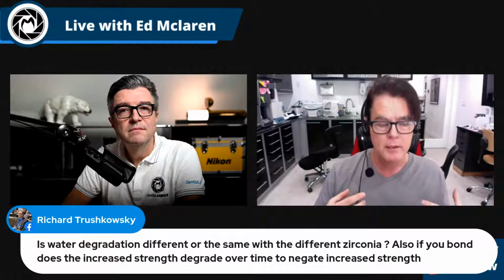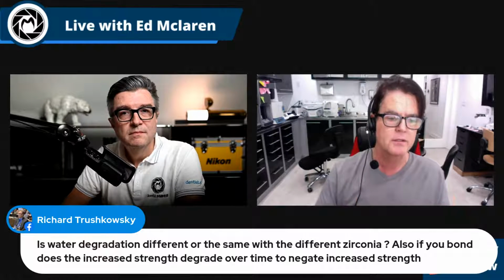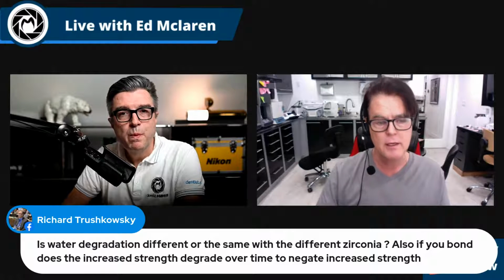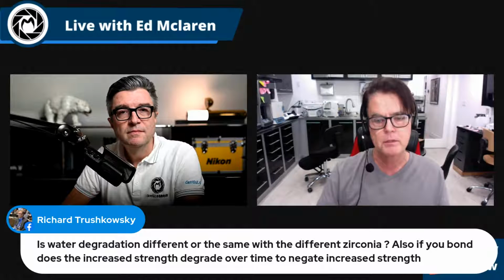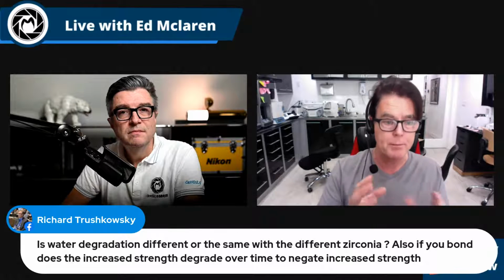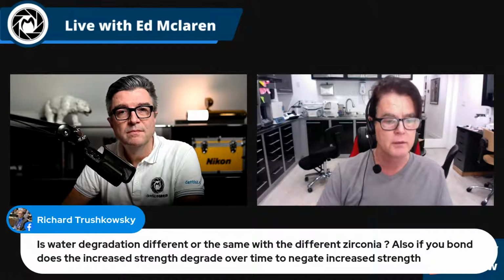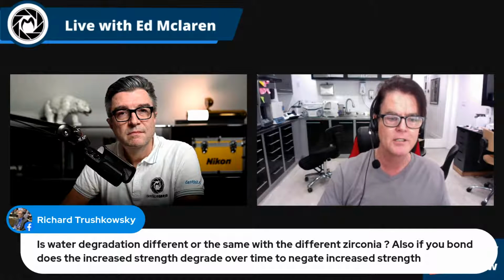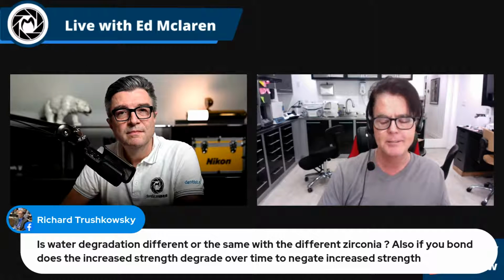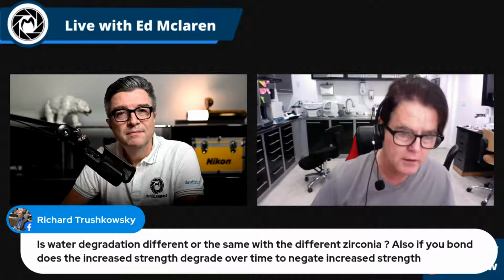From the information that we see right now, I don't think I would be fast sintering a bridge. Because if we've created an environment where this low temperature degradation can potentially take place, it could probably happen in connector areas and cause fractures, right? So I would do normal sintering for a bridge for sure. Now remember the point I made before, the 5Y materials don't have low temperature degradation because they have too much cubic phase in there. When you get more than about 30% cubic phase, you lose the ability to have this phase transformation. So there's a good and bad of a 5Y material. The 5Y material doesn't undergo low temperature degradation, but if you sandblast it, it weakens it, okay?